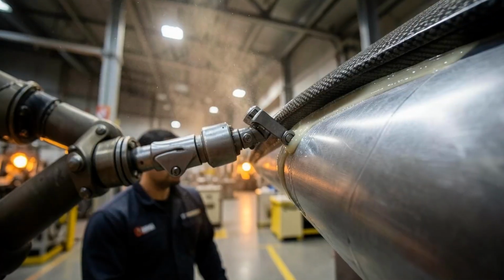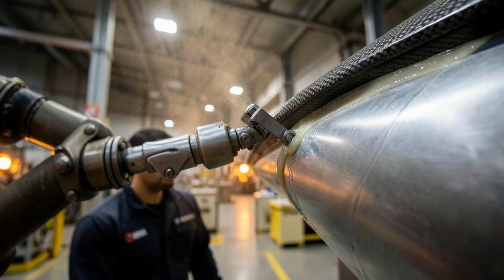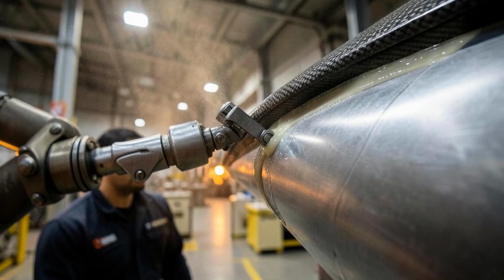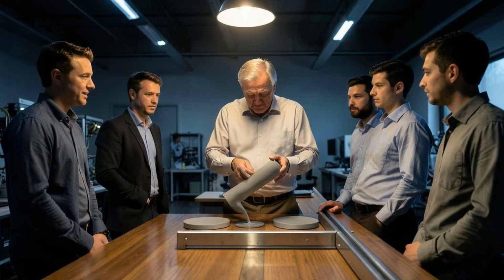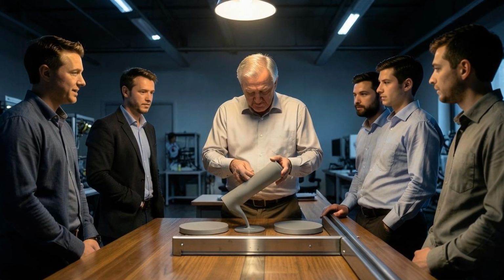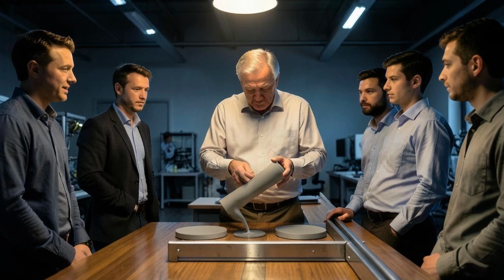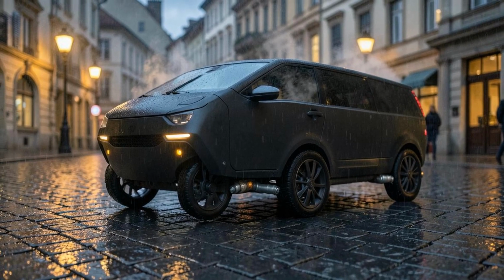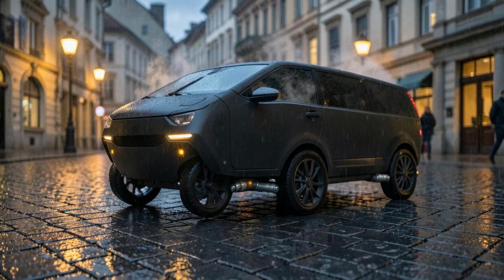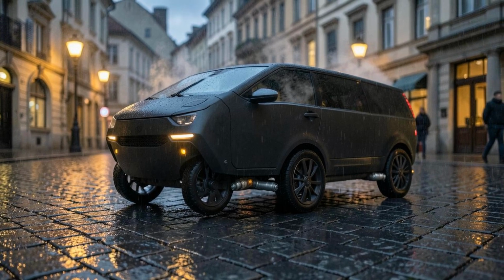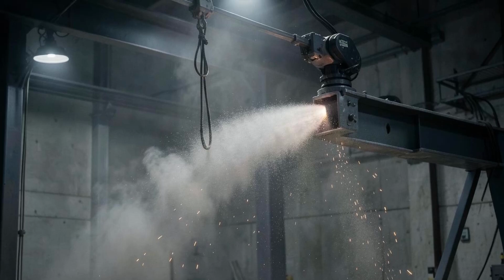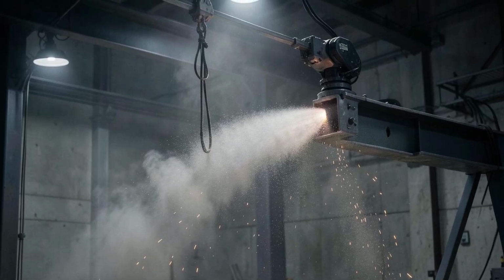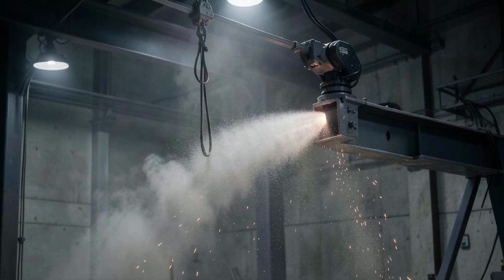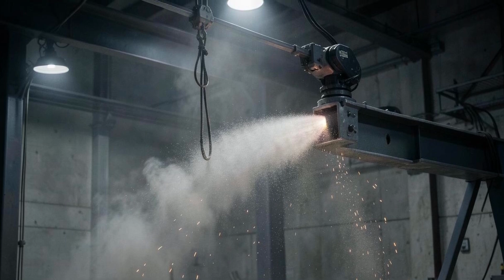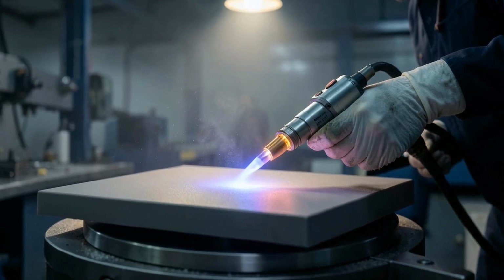The solution is not to stop using carbon fiber or stainless steel. It is to change how we design the bond. You must account for the thermal mismatch by selecting adhesives with a lower modulus of elasticity. These adhesives are more flexible and can absorb the differential movement without transferring the full stress to the interface. You must also implement a multi-stage surface preparation protocol that goes beyond standard cleaning. This includes controlled abrasive blasting to create a specific surface profile, followed by a plasma treatment to activate the polymer